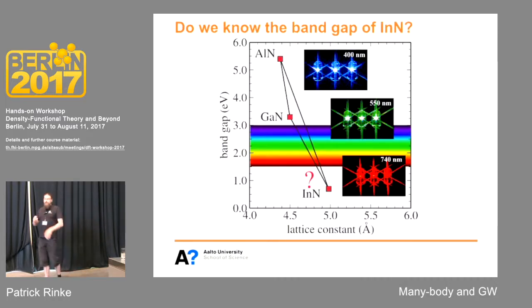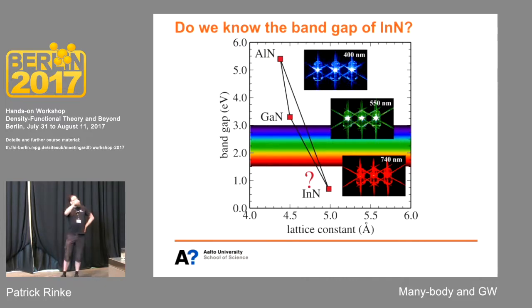So the problem that I brought along that I'll come back to is this one, very simply. The nitrides were, and are, a very good solid-state system for these applications because aluminum, gallium, and indium nitride all crystallize in the same crystal structure. If you remember the talk this morning and maybe the exercise you did in the last couple of days, we can mix these material systems and create intermediaries, alloys, that then have the desired properties. The property we're after here is the band gap, and we would like it to be in the visible region for a display or an LED or laser application. The nice thing is that the band gaps of gallium and indium nitride straddle this optical region. So if we mix appropriately, we can go from blue to green to red.